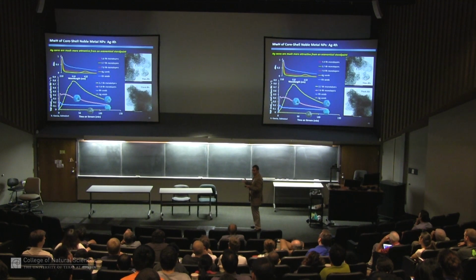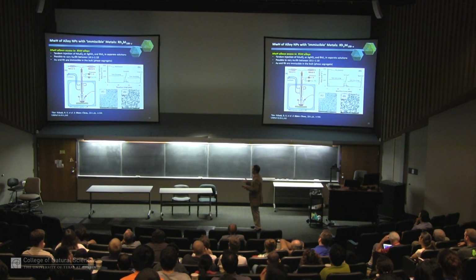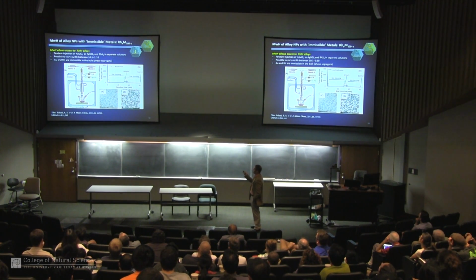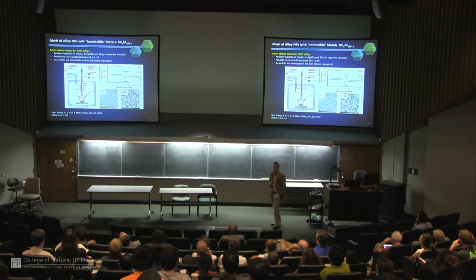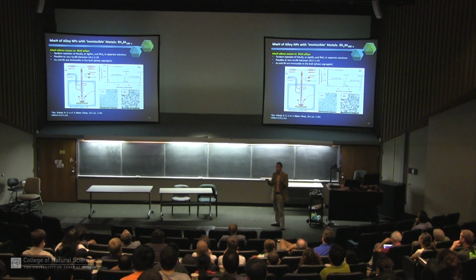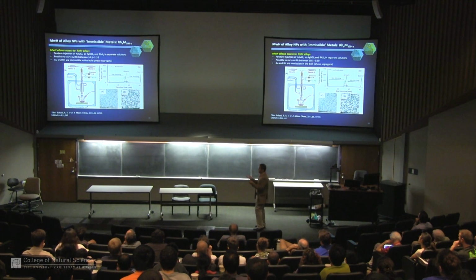Well, she did that, and she's very diligent. She was great in the lab, fantastic student, and she came back and said, all the spectroscopy says they're alloys. No, these alloys don't exist. But sure enough, in the microwave, and you can't do this conventionally, you can make alloy nanoparticles with random structures with these combinations of metals. They are stable on the nanoscale because presumably something unique is happening on the nanoscale that's allowing them to be metastable. If we grow them big, 30 or 40 nanometers, they phase segregate, which plays along with what you would expect classically. You wouldn't want particles that big because they're just useless at that point anyway, but we can make very stable particles that are 5 to 10 nanometers in size and do chemistry with them.